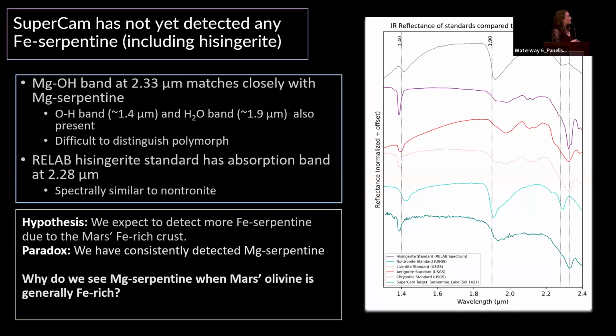And so here on the right, I have a few different standards. On the top is hisingerite. You can see the band at 2.28. And here we have the 3 magnesium-rich serpentine polymorphs, and they have bands at 2.33. And we also have nontronite just to show the comparison. But here at the bottom is the SuperCam target, actually called Serpentine Lake, which was pretty cool. And you can see it has a band at 2.33. So it matches much more closely with the magnesium-rich serpentine.